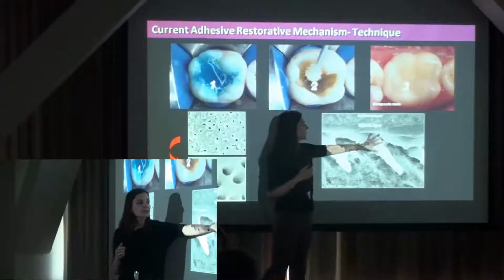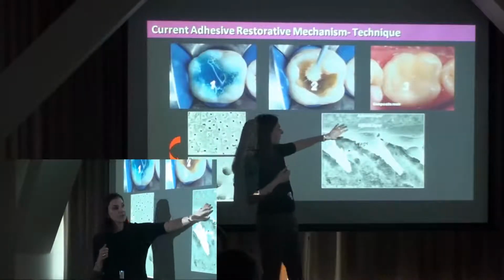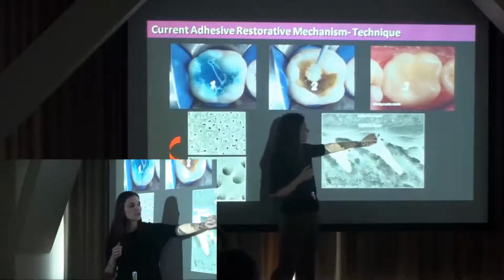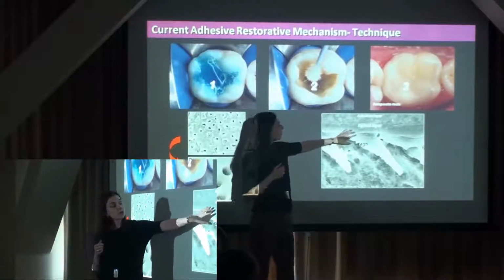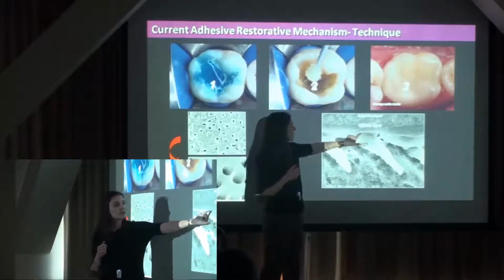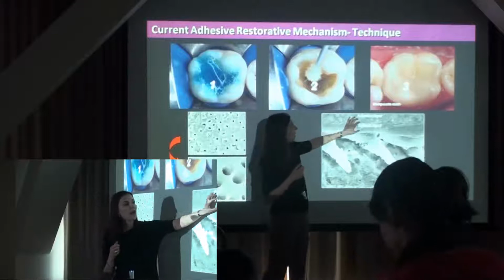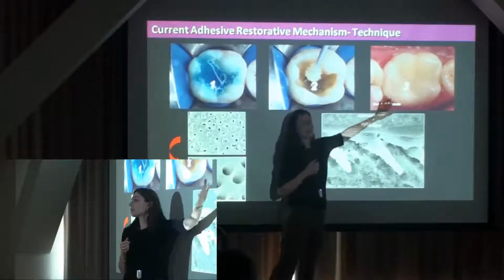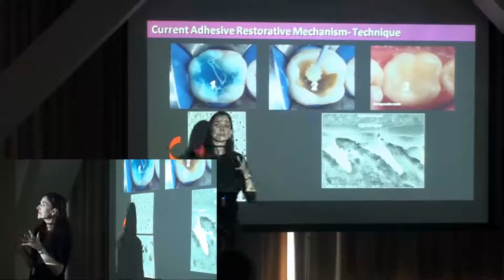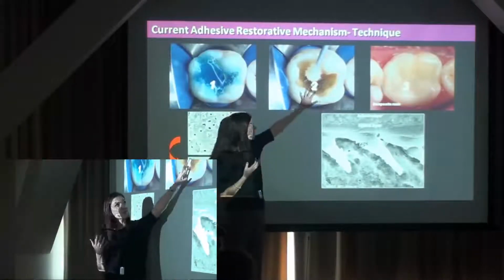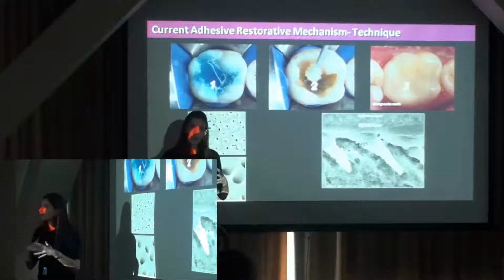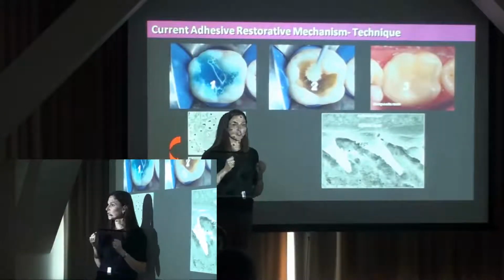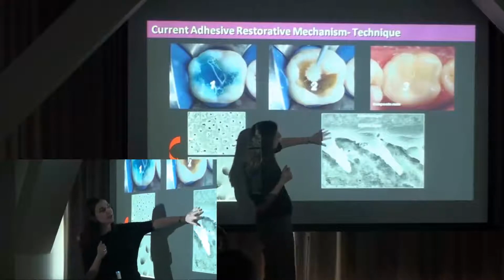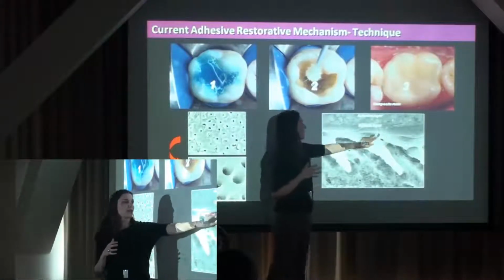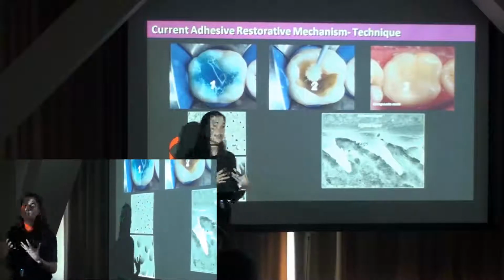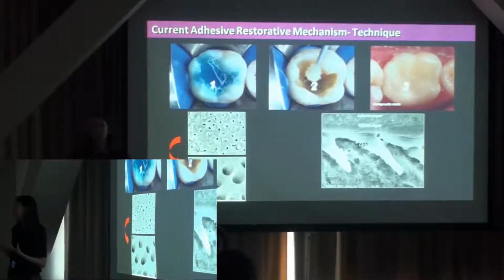So what we have here when we look at this interface is a material that had the ability to infiltrate. Some of it goes into these tubules, and most of it will infiltrate into that collagen and create this hybrid layer. On top of that, we have a layer of adhesive and then the layer of this composite. So we have all these phases. And this is done, so you have an idea, this process here is done in about 20 to 40 seconds. So it's a very quick sort of tissue engineering that we have. And 80% of the bonding comes from this layer. So without properly making this hybrid layer, these materials are going to fail a lot quicker.